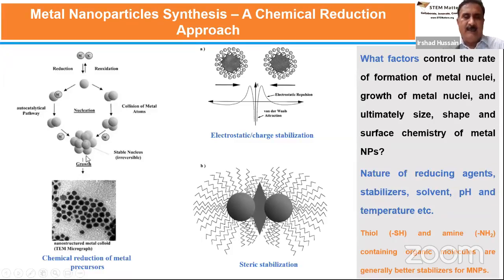But in order to make nanoparticles, you really need to control the nucleation, that is the formation of these nuclei, and then further growth of these metal nuclei into nanoparticles. So basically, there are two processes that we need to control, that is nucleation and growth of these nanoparticles. For example, if we use strong stabilizers or capping agent during the synthesis of these nanoparticles, like those molecules which have, for example, thiol functional group or amine functional group, they will immediately cap these nuclei at very early stage, and they will result in the formation of very small particles that we call nanoclusters.